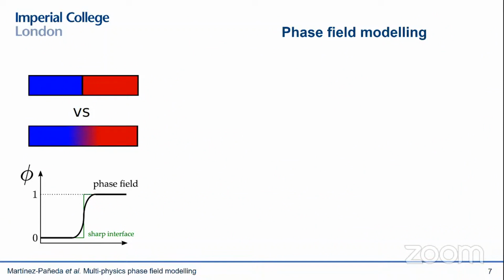So whenever you have an interface, or whenever you have two phases, you can describe the interface as either sharp and discontinuous, or instead you can smear that interface over a finite domain using an auxiliary variable, the phase field, and then track the evolution. Basically this phase field will take two distinct values in each of the phases. So it can be 0 in the blue phase, 1 in the red phase, and then it will vary smoothly between. And then you just need to solve a differential equation for the phase field, and you're able to track the evolution of interfacial problems of arbitrary complexity.